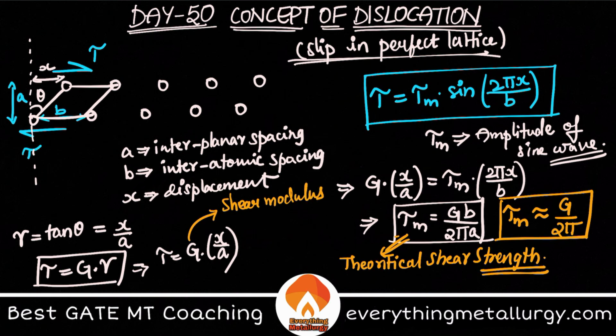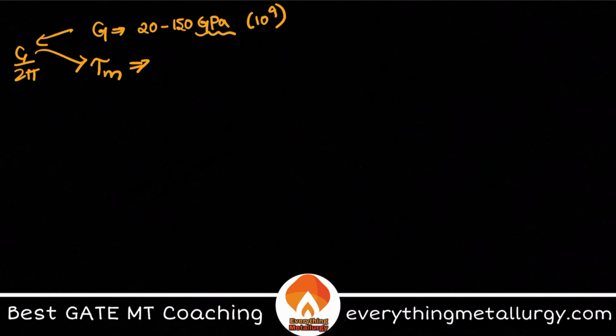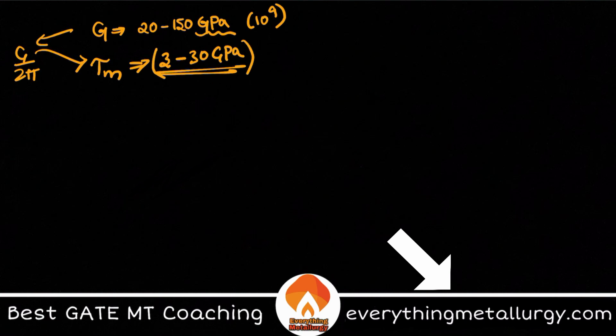Okay, so G is actually in the range of about 20 to 150 GPa, gigapascal, which is on the order of 10 to the power 9. But the theoretical shear strength, when we calculate taking G by 2 pi, should be in the range of about 20 by 7, so approximately 3 to 30 GPa. Let's assume this is the amount of stress that one has to apply on a material in order to produce the shear displacement.